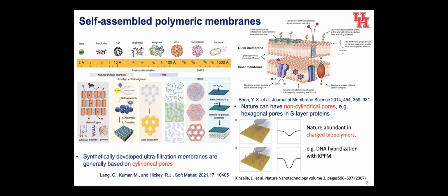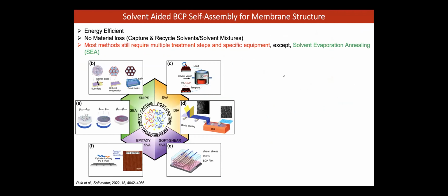Finally, there is charge. I'll show at least one illustration of how separation of liquids by way of shape, size, and charge is the next generation of membranes that we need. With that background, we do a lot of solvent casting, and in the end you want it to be as simple as possible. In previous methods, you cast the block polymer from a common, good solvent, like toluene, that can dissolve polystyrene, PMMA, or many other types of block polymers.